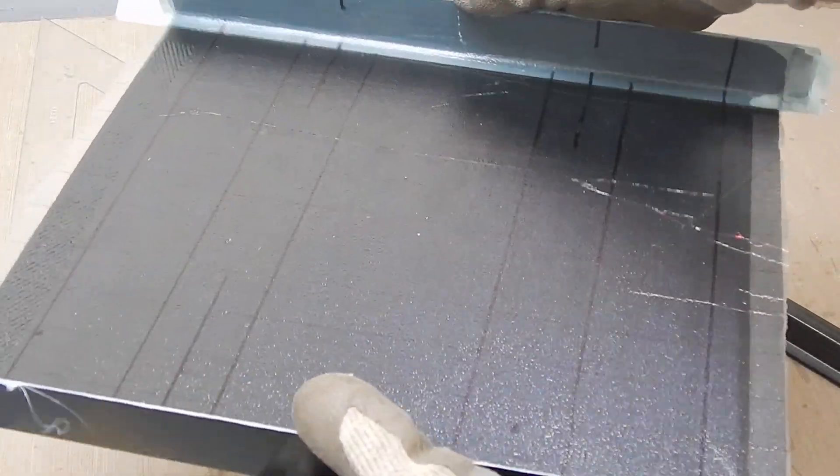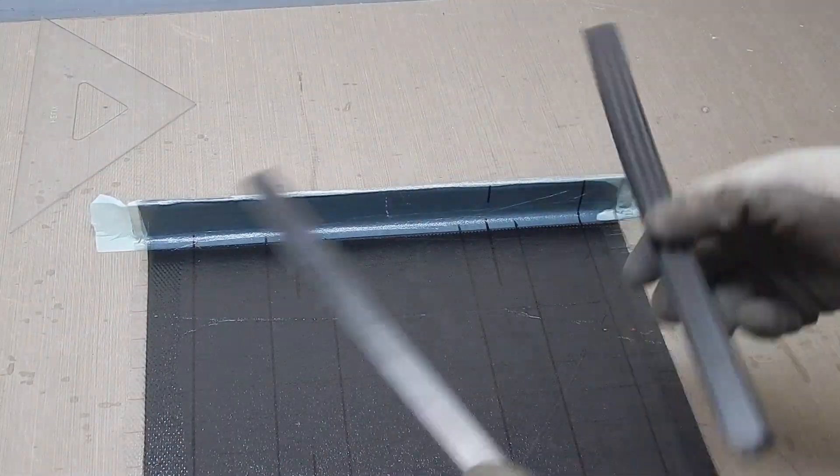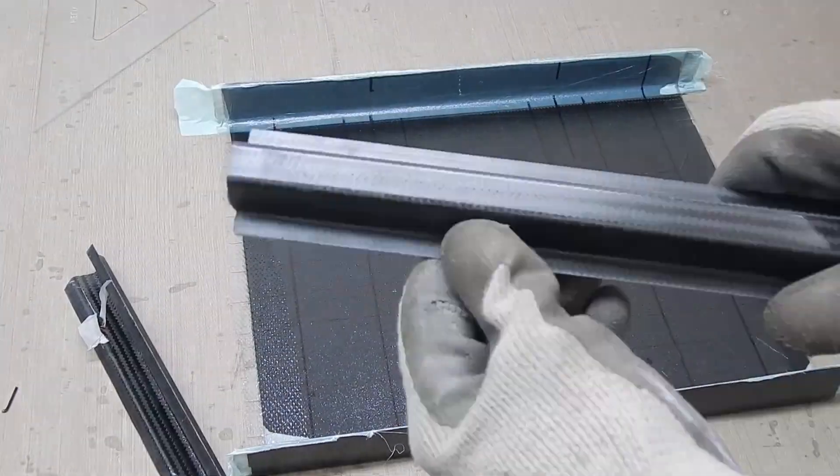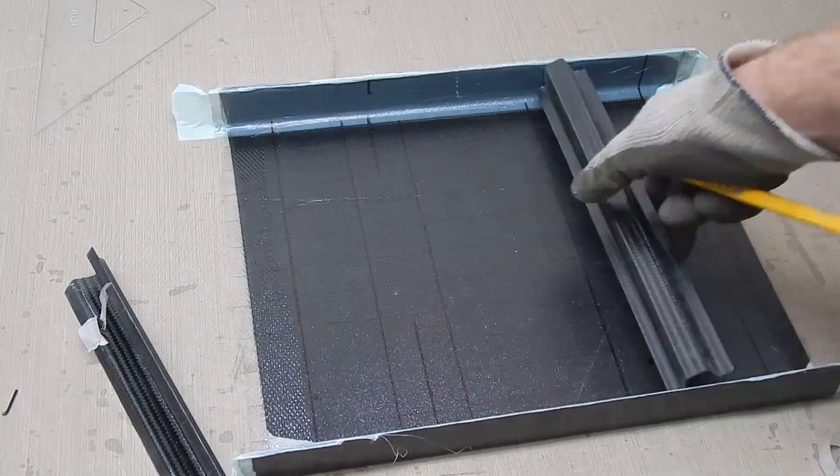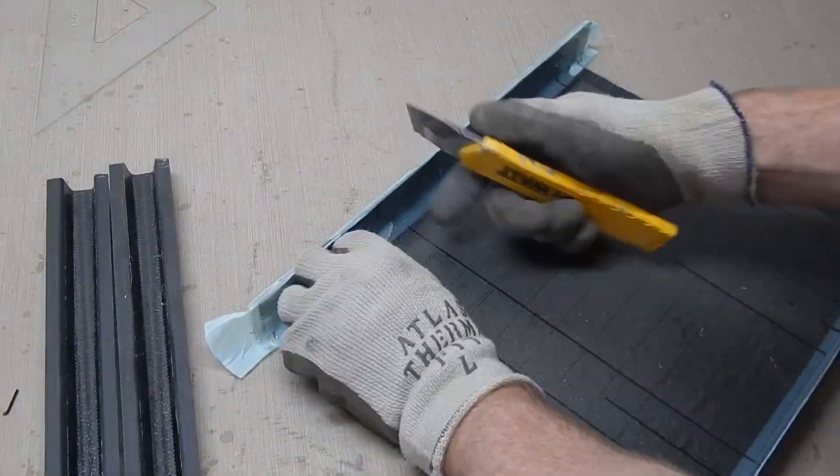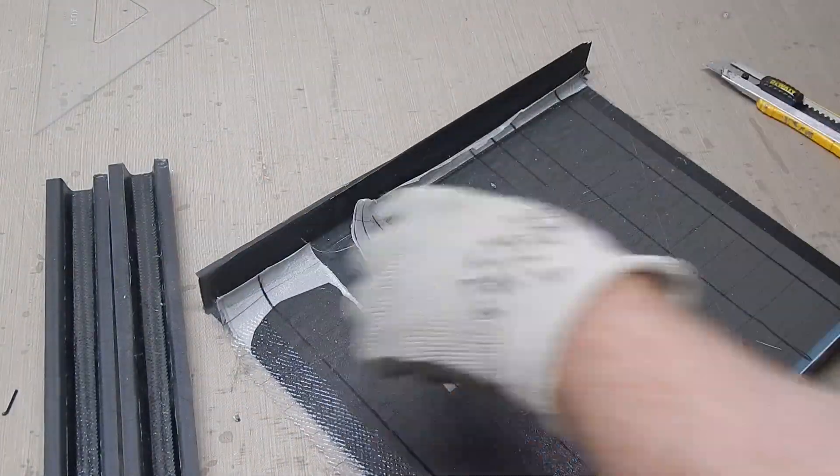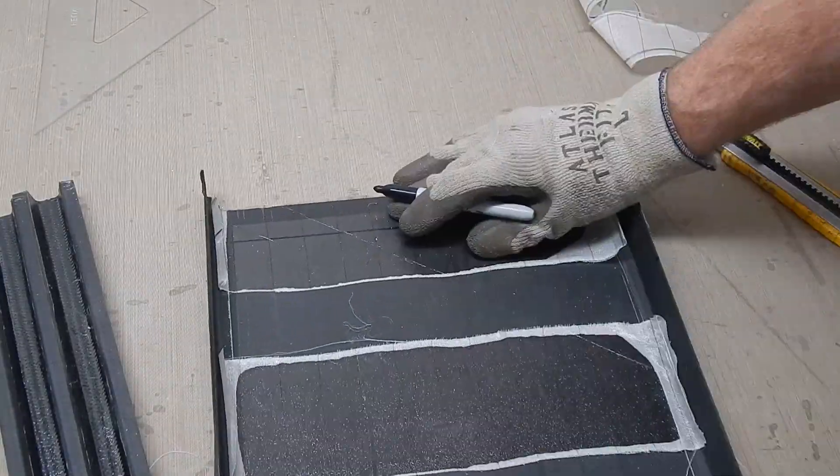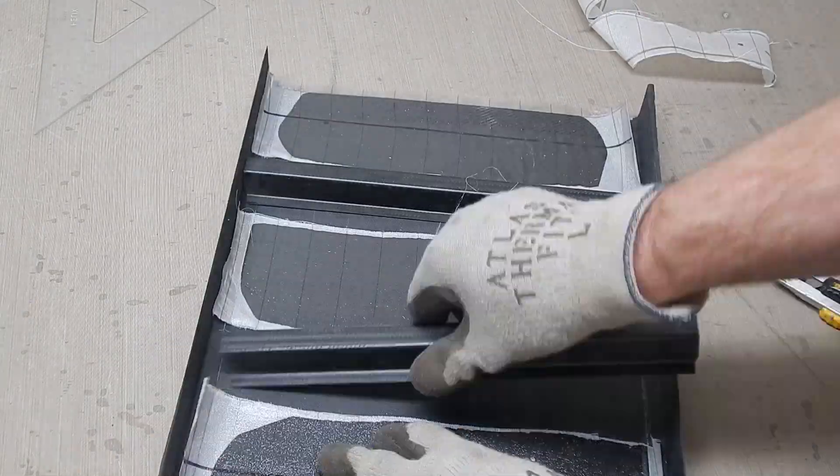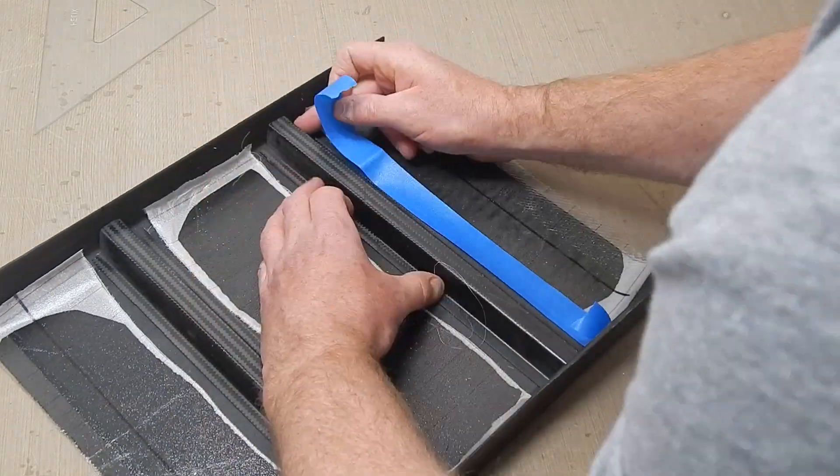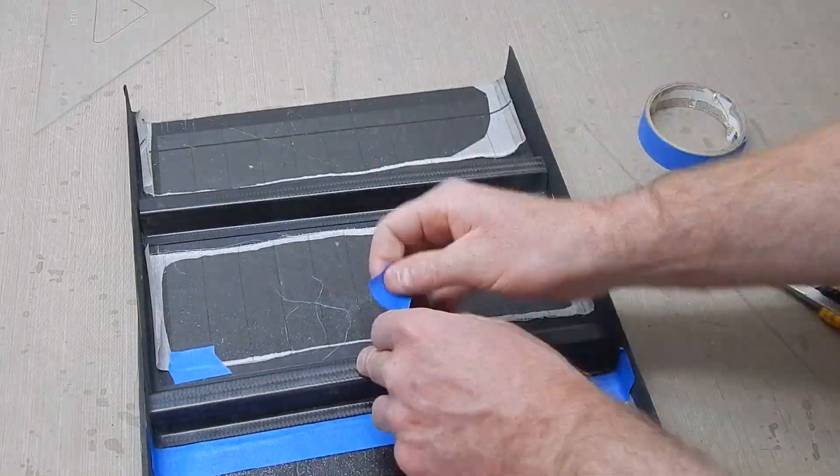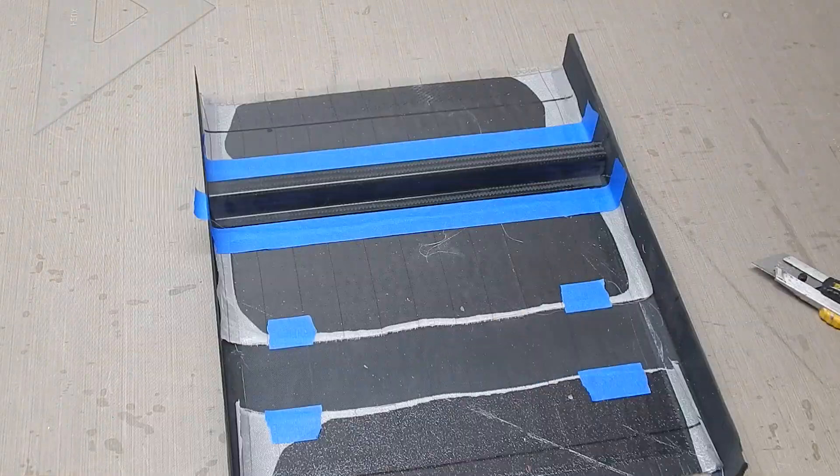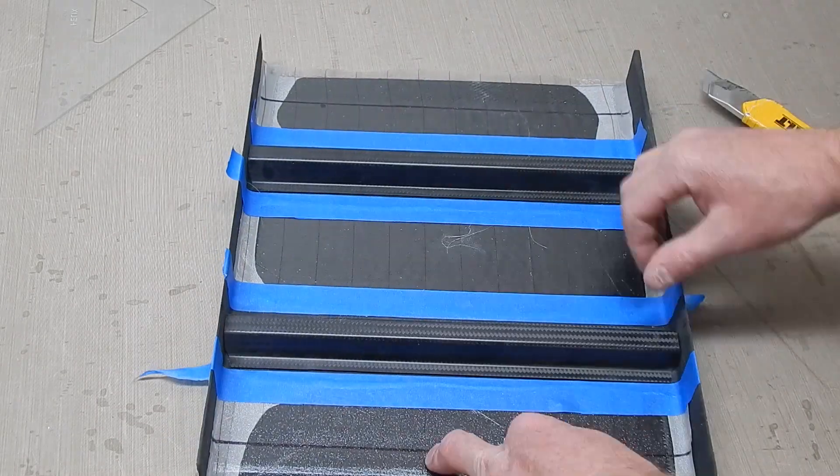So here's the trimmed part. And I've decided where I'm going to place the pieces of structure. Little omega channels. And laid it out with Sharpie. Peeling the peel ply off the little channels here. That leaves a nice surface. I'm not going to do any sanding to prep or anything like that. I'm just going to pull the peel ply and go. And so I'm going to leave the peel ply on the panel where the parts aren't going to go, just to protect it. This is a good idea. This is a little silly to do it on a part this small, but I'm doing it anyway just to show that it's a good idea. I placed the channels where they're going to go and marked them off with masking tape. And then masked off the panel so that when I apply the adhesive it will not go everywhere.